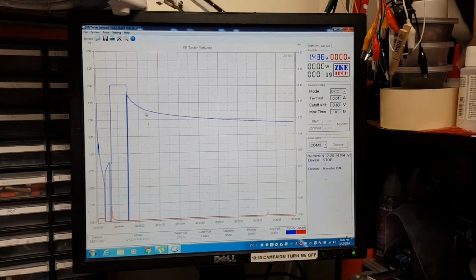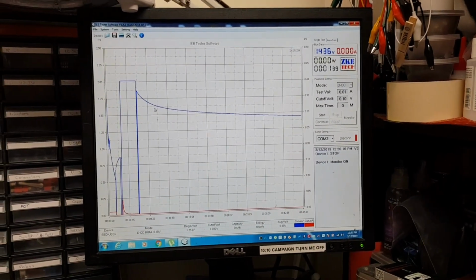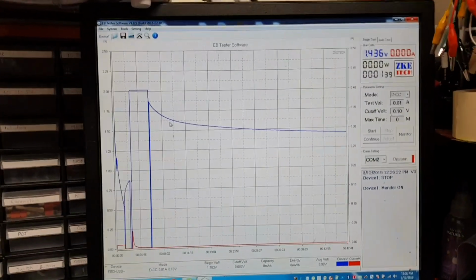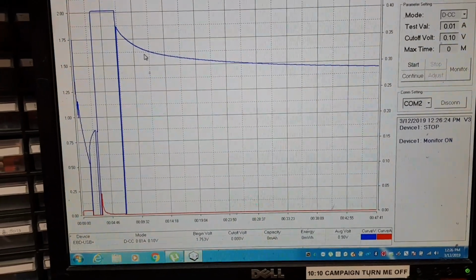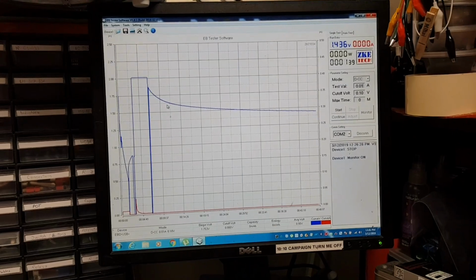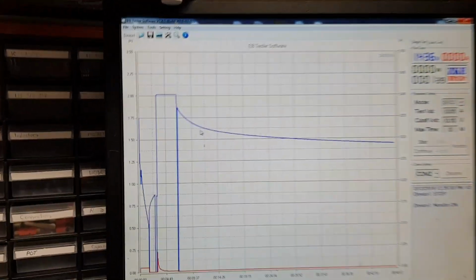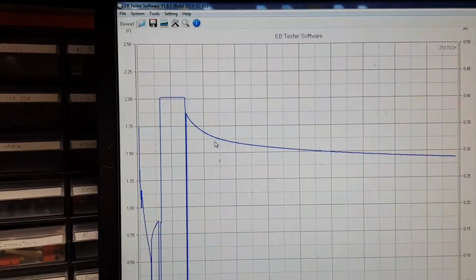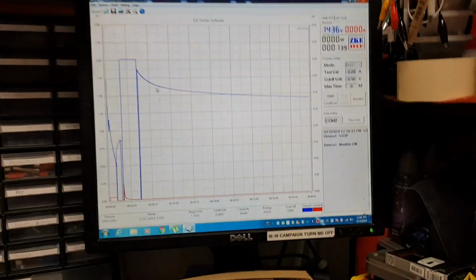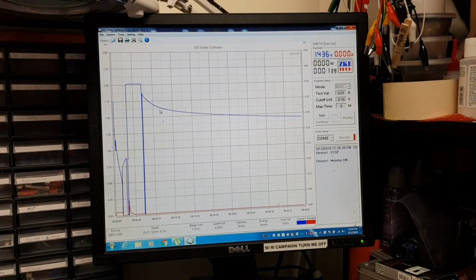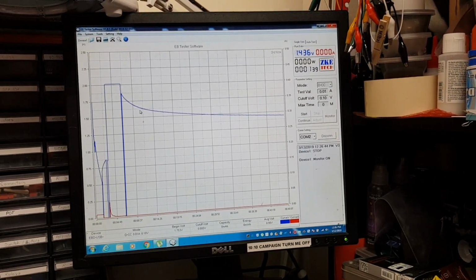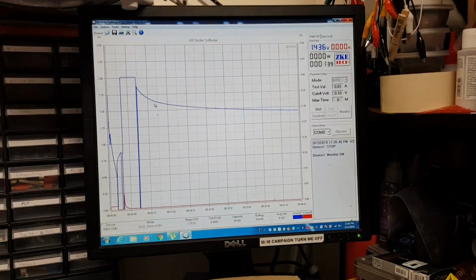Interesting recovery. I had to go to the vet. I've charged the cell after that drastic drop, and it's probably been around 40, 45 minutes since I charged it. After the charge it was on 1.8 volts, and half an hour later, it's still on 1.3 volts. And it's holding this value pretty well.